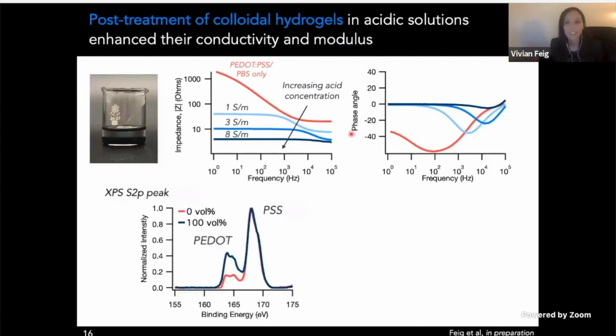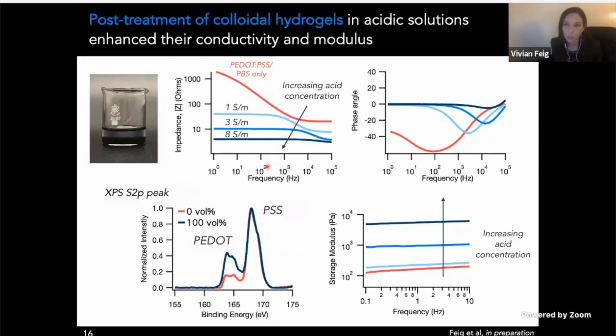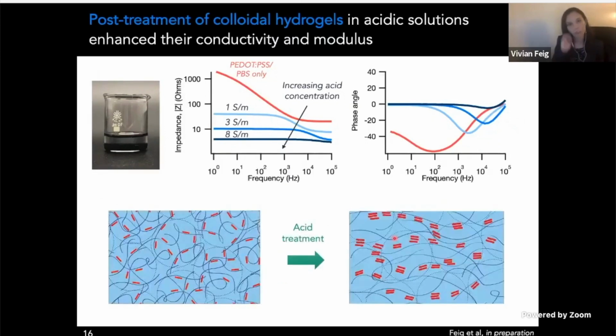Analogous to the thin films, we also see that this post-treatment can allow us to remove some excess PSS, as seen by this relative increase in PEDOT to PSS ratio again. And finally, as we lower the impedance of the gels, we're also increasing the storage modulus, which suggests that these new conductive junctions that are being formed in the material are directly also contributing to the elasticity of these polymer networks. So therefore, just like we can directly form these highly conductive gels through blending with the ionic liquid, we can also take something that's less conductive and use post-treatment methods to enhance the conductivity of these already formed soft gels.